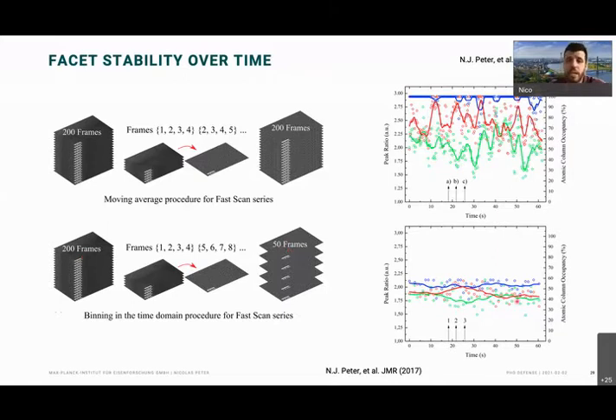And if we analyze this, then we see, well, there's a complete collapse of the signal. We cannot extract any meaningful thing here out of the data. So if you like to do that, always keep in mind that in TEM, things are pretty mobile and move around a lot. So you need to have pretty high frame rates to do such things.